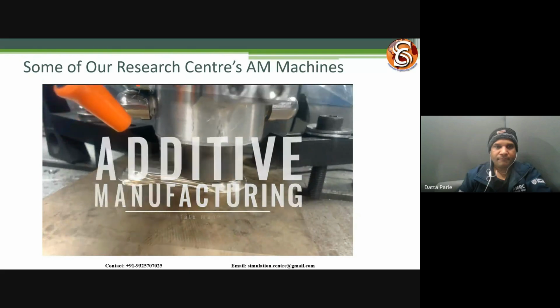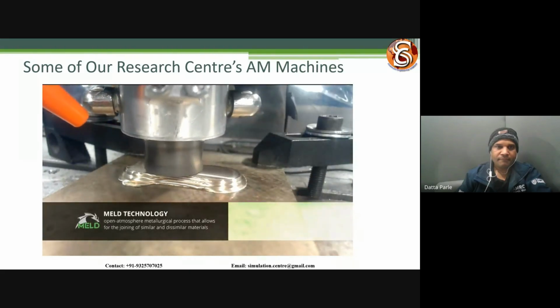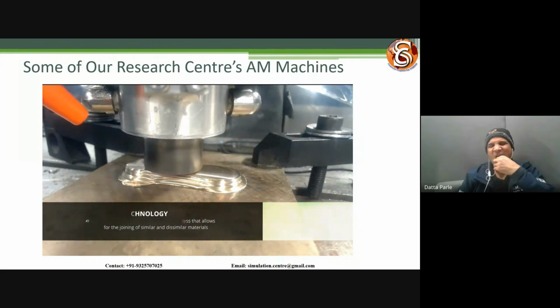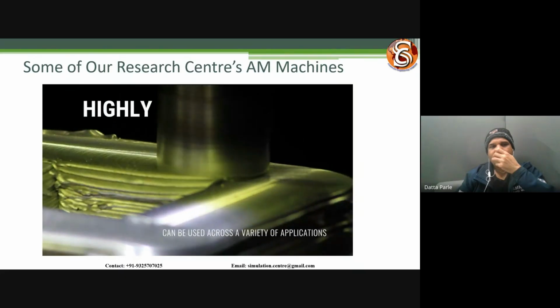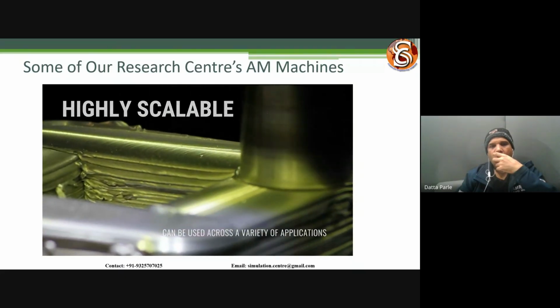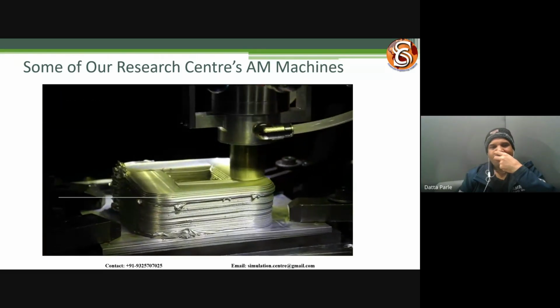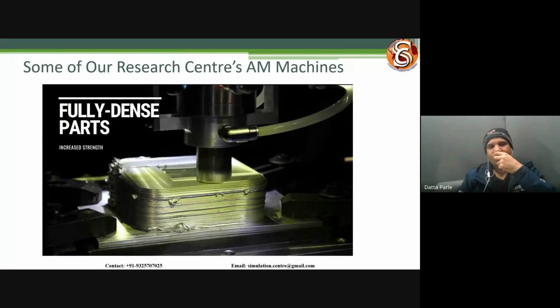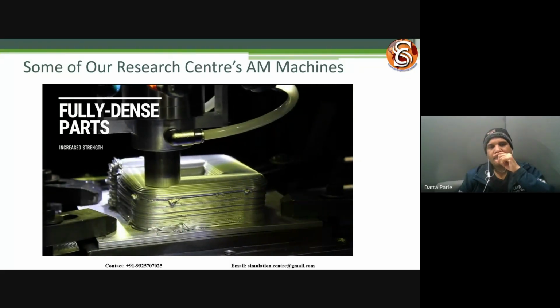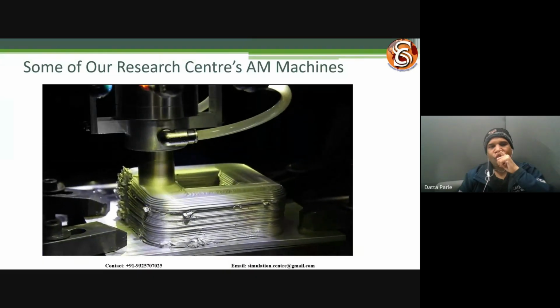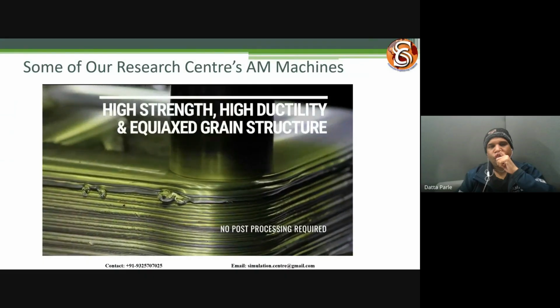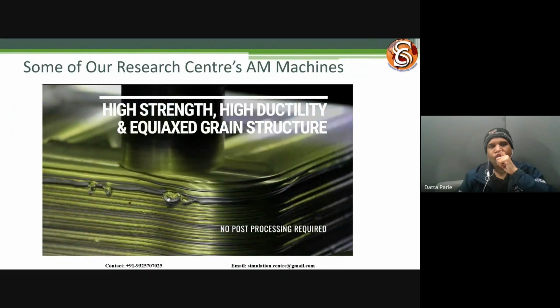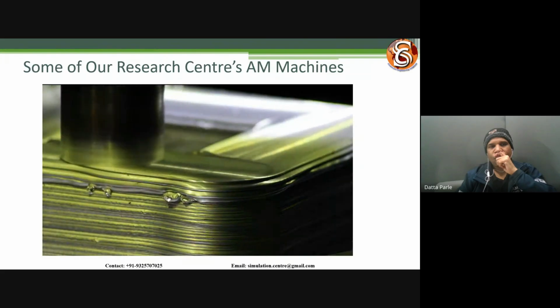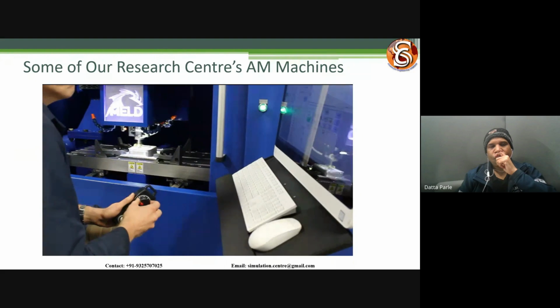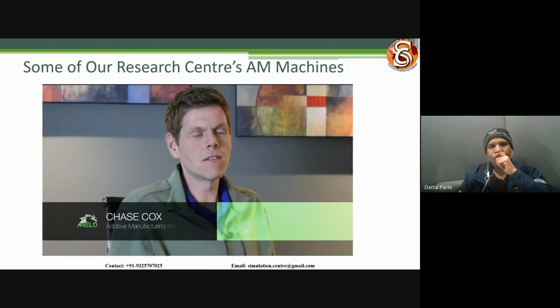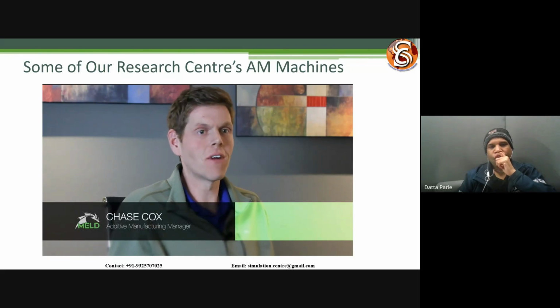What makes the MELD process unique is that it's solid state. There is no melting. We stay below the melting temperature. And this is what results in a number of really great characteristics in the build. Not only do we see really great material properties, but our deposits are also fully dense, meaning that the part doesn't require a secondary step. And there's very little waste. It's a very green process. We're very passionate about the MELD process, and we're very driven to see it take off and proliferate throughout industries.